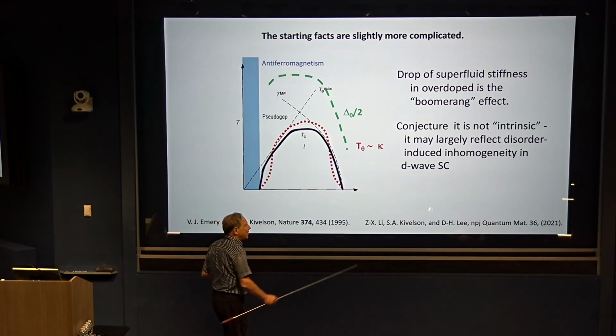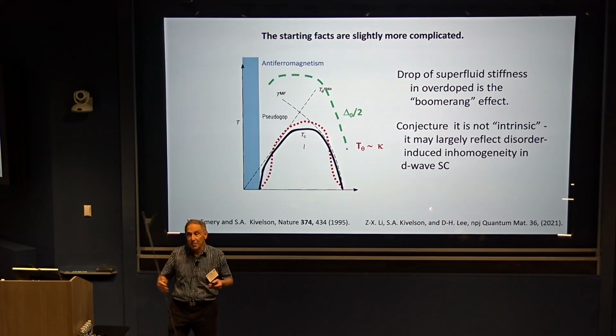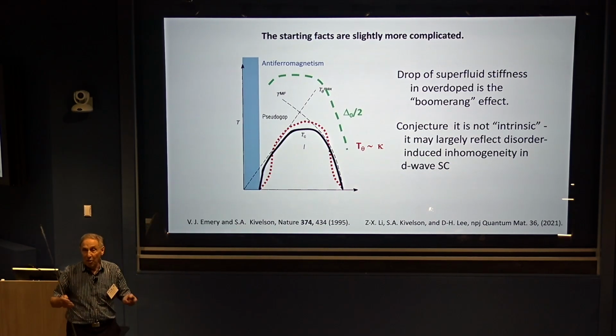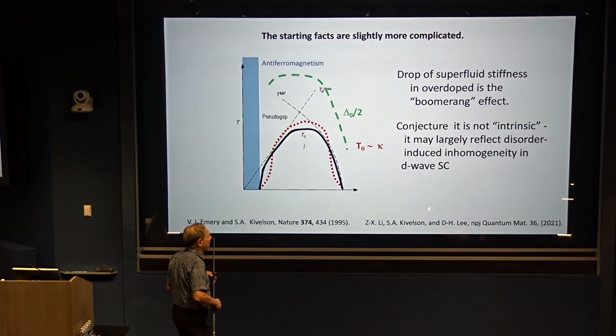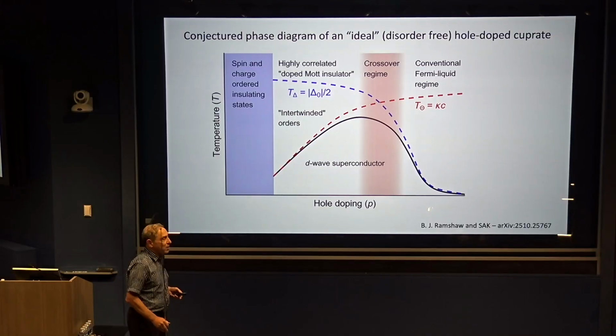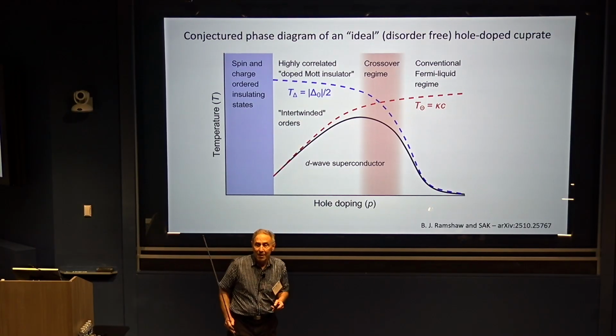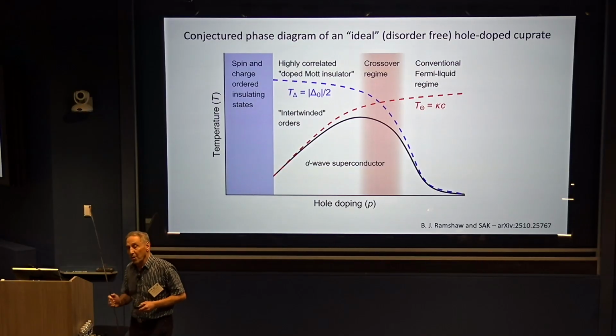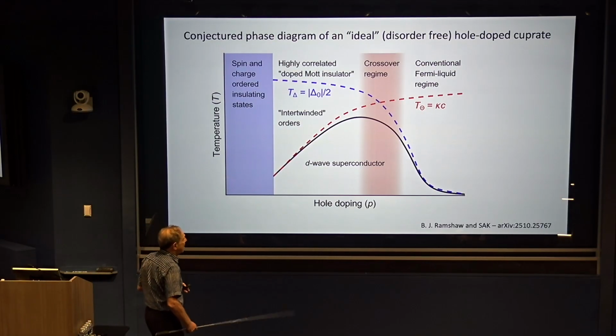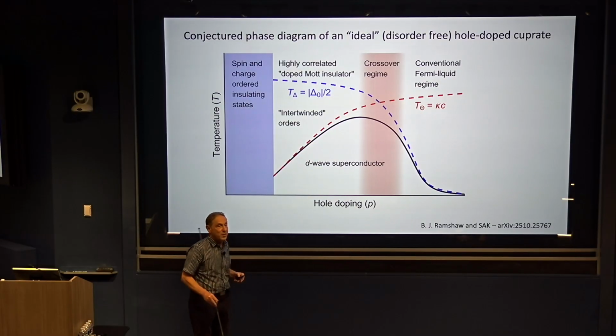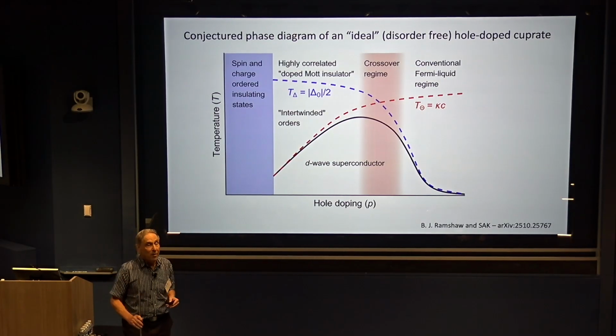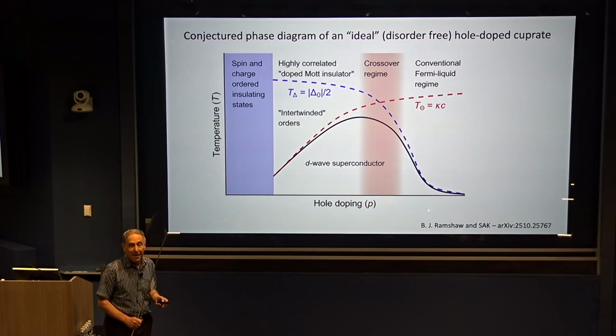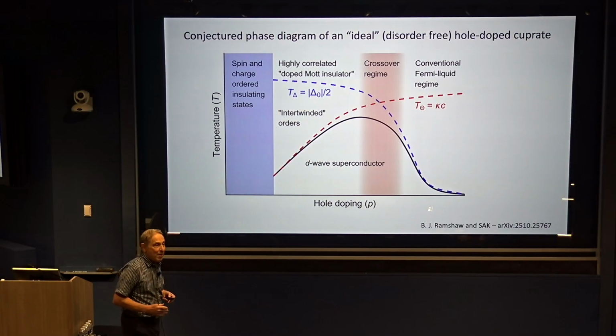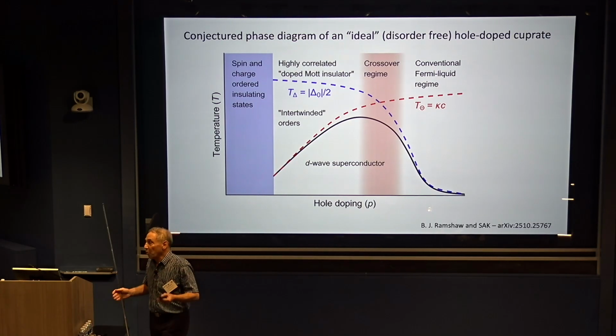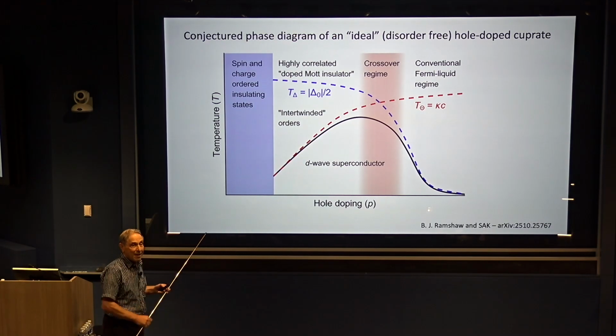We've carried out calculations to at least show that this is plausible, that you get sort of self-organized granularity over here, which was responsible for a big suppression of the superfluid density. So what I'm going to do is to imagine that the cartoon, or here's an updated cartoon in a recent perspective that was posted recently by Brad Ramshaw and me. So this is what my claim is, that the phase diagram of a clean, disorder-free cuprate would look like.